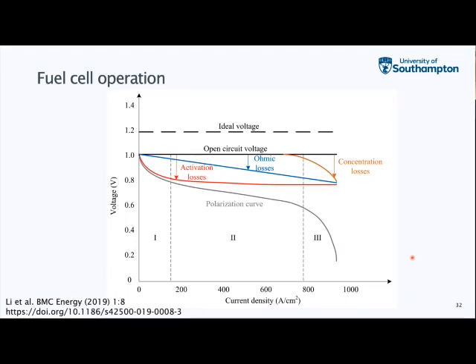In terms of operation, similarly to batteries, the open circuit voltage is always lower than the ideal, and then as you start to operate the system and draw current, you get a polarization curve that is made up of a number of losses. There's ohmic losses, activation losses to do with the kinetics of the reaction processes, and then concentration losses. So at very high currents, you are starving the reaction sites of hydrogen and oxygen, and so you have mass transport limitations. So you've got effectively three regions where in the first one the activation losses associated with the electrochemical reactions dominate, and then a steady ohmic loss before you get into a mass transport controlled region where you are limited by the supply of hydrogen and oxygen to the catalyst centers.